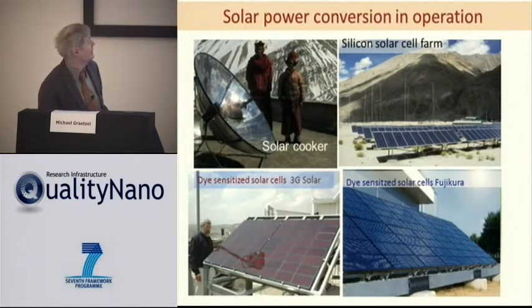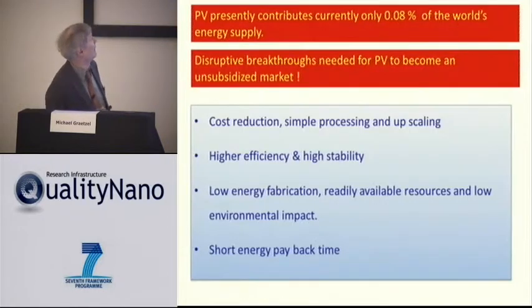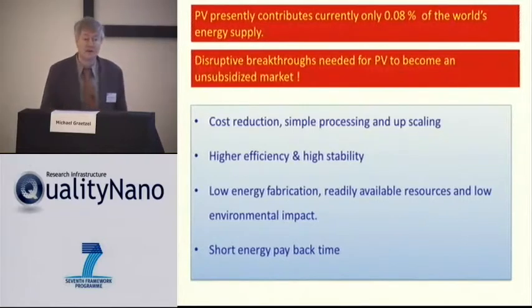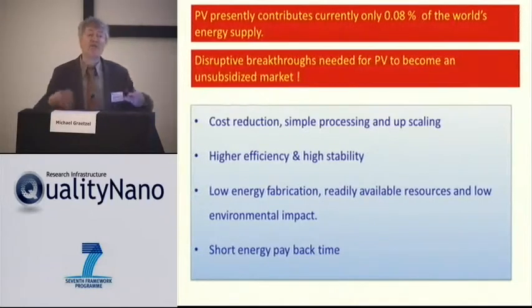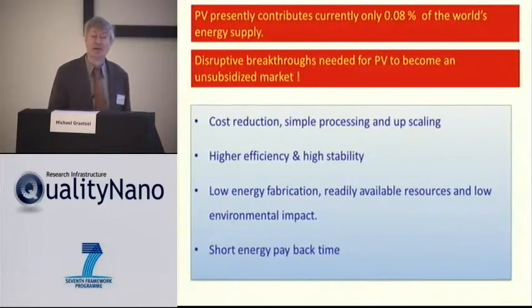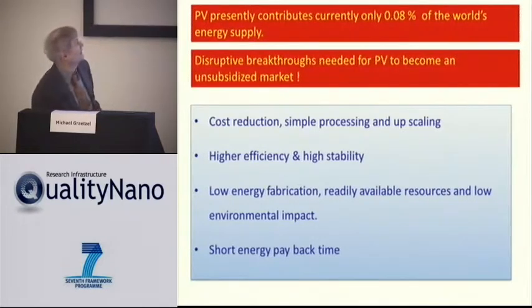And these are some of our cells that are being tested. Here, this is a test station in Jerusalem, and this is in Tokyo, Japan. And so, as I said, the contribution of PV is very, very small at this stage. So the whole thing, it's an open game. It's not a game that is settled. It's starting. So you want to go from these 0.08%, somewhere to a few percent, okay? It would be nice if you got 25%. That's a huge scale-up. And so the scale-up is at least by a factor of 1,000, okay? So here are some of the evident requirements we need to realize those targets.